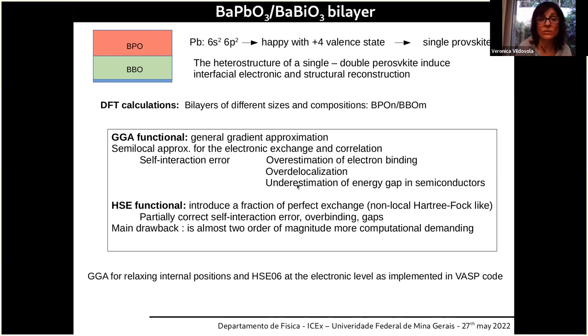The first approximations were local approximations. One of the most used is called the generalized gradient approximation. It's a semi-local approximation for the electronic exchange and correlation potential. Due to these local approximations, it has some self-interaction errors. And these self-interaction errors induce some overestimation of the electron binding, some over-delocalization of the electrons, and consequently some underestimation of the energy gap in semiconductors.